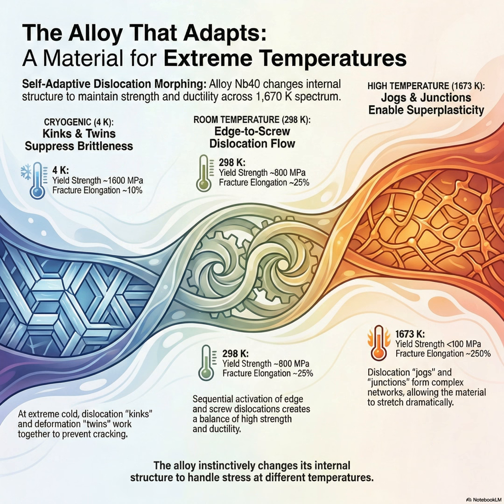What's the core dilemma here? Why do metals normally fail at these extremes? It all comes down to their crystal structure. When you cool a conventional metal way, way down, its atoms have less thermal energy. They can't move around. The whole lattice just locks up. It locks up. And when you apply stress, it can't bend or stretch plastically. It just cracks. Catastrophic failure. That's the classic ductile to brittle transition.